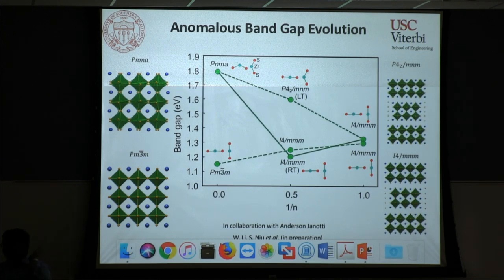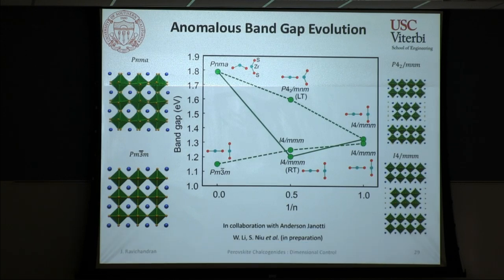So that's something that we found interesting, and perhaps that's a mechanism that one could use to tune the optical band gap, and hence make different heterostructures of these materials.